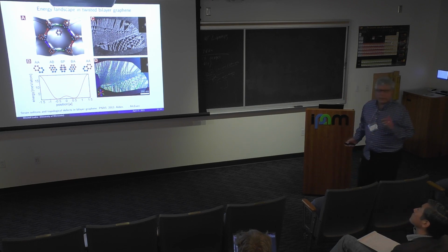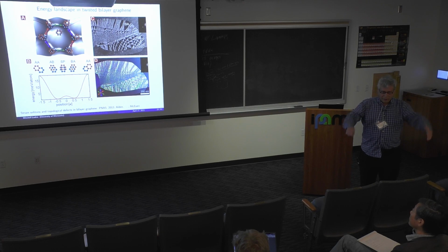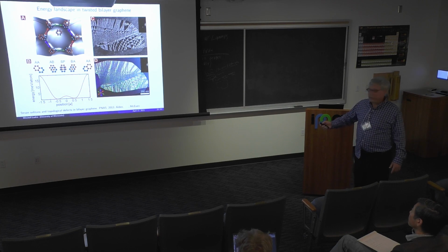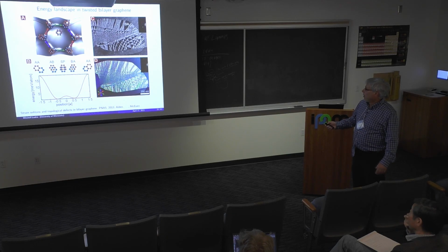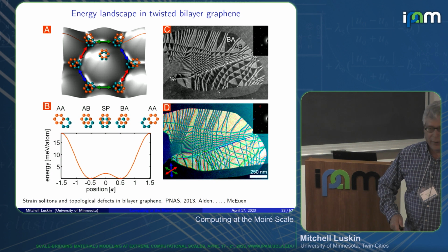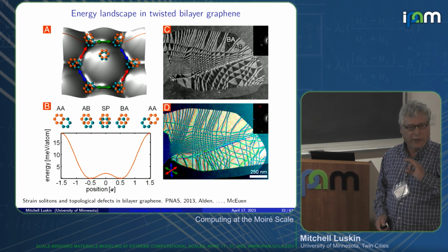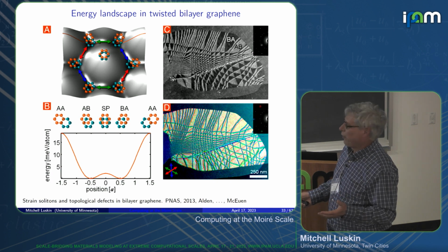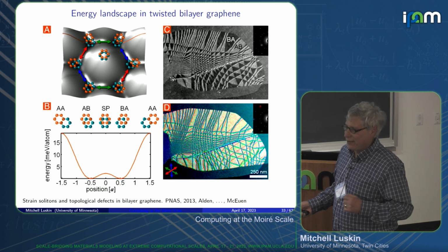In experiments, right, typically what you have is electron diffraction. And so you have these diffraction peaks, and that's really your information. It turns out to be an interesting problem when you have relaxation. But you can then take your diffraction, zoom in a little bit around one of the peaks, inverse Fourier transform right back, and you get this dark field imaging, which is an amazing process.